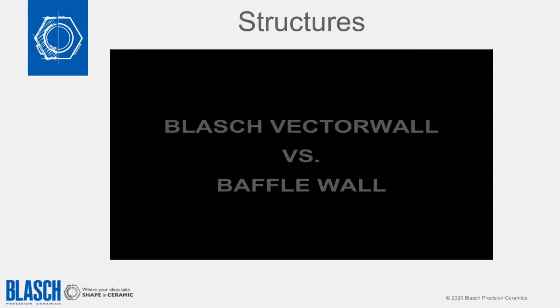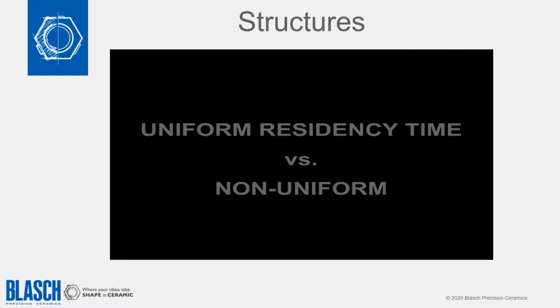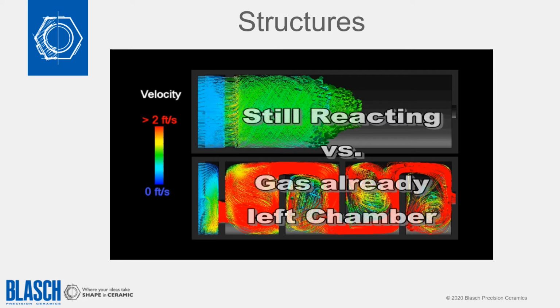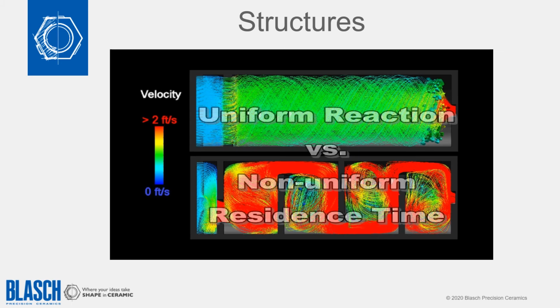I'm going to show a little short video of a comparison we did between a baffle furnace and a VectorWall. And this is where it first dawned on us that this residence time distribution was the problem. These baffle furnaces, which are typical of sulfuric acid plants, are great mixers, but they really increase the residence time distribution. They really force the designers to build much longer furnaces so that the material that exits that much more quickly still has a distance to travel to exit the furnace. So you're adding walls, you lengthen the furnace, you add a wall, you lengthen the furnace. It's sort of a self-defeating experience, whereas with the VectorWall, the plug flow is proceeding at ideally about the rate you need it to proceed to just complete the reaction as it leaves the furnace.